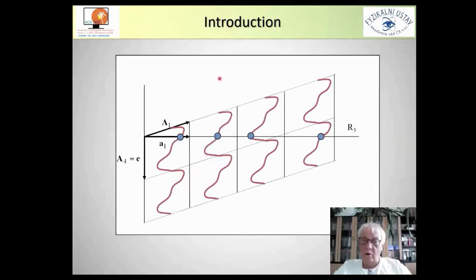Here you can see an example of positional modulated structures as described in this artificial direct two-dimensional space. You can see that in the first cell, the second cell, the third and fourth cell, these atoms are located at different positions. But the description of this artificial cell in direct space shows some modulation curve, and from this curve we can in fact derive all positions of atoms in the actual cell. Because of this translational symmetry, we can move the atom position of the second cell to the first cell, and by translational symmetry from the third cell to the first cell again, and the same with the fourth cell.